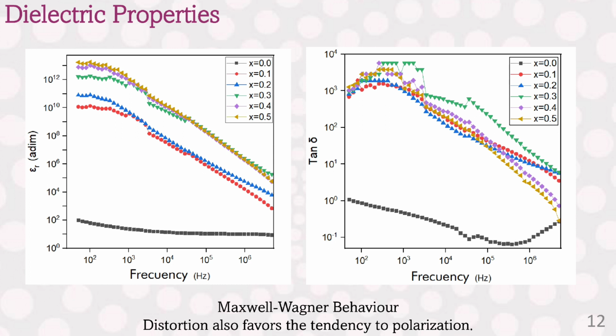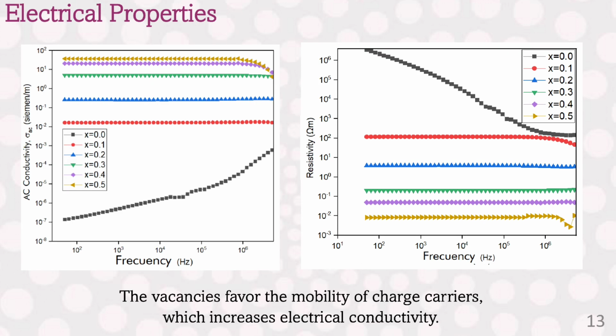The behavior can be associated to oxygen vacancies that could be generated to compensate the charge by the difference between Fe3+ and Ni2+, which can generate the presence of Fe4+ that, when forming bonds with oxygen, can polarize when subjected to an electric field. The vacancies favor the mobility of the charge carriers, increasing the electrical conductivity.